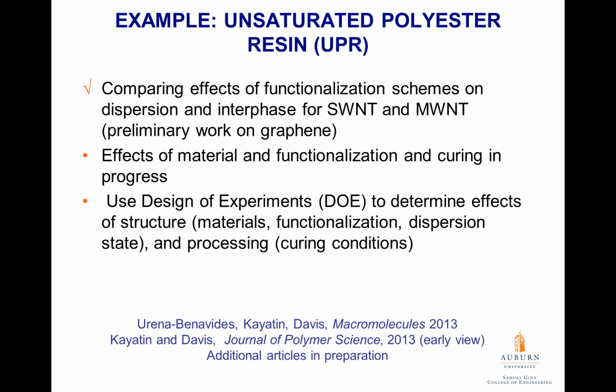So far what we've done is compare the effects of functionalization schemes on dispersion and the interface for single-walled carbon nanotubes, or SWNT, and their nested analog multi-walled carbon nanotubes, or MWNT, and we've also done some collaborative work on graphene. Now we're looking at how these chemistries affect our curing process, because obviously for a thermoset resin, the way we cross-link and cure it is also going to be very critical to properties. And then we'll use design of experiments to determine the combined effects of the structure, that's materials functionalization and dispersion state, and processing or curing conditions.